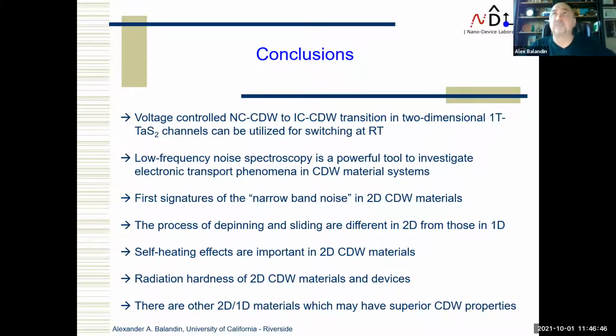And I'm coming to conclusions here. We came up with devices, switches, which have functionality completely different from transistors, and also different from resistance switching. This functionality is based on quantum mechanical phenomena, which could be observed at room temperature and has a high degree of coherency, so the samples could be large. We also proved that low frequency noise spectroscopy is a powerful tool to look not just for the quality of materials, but also for phase transitions.